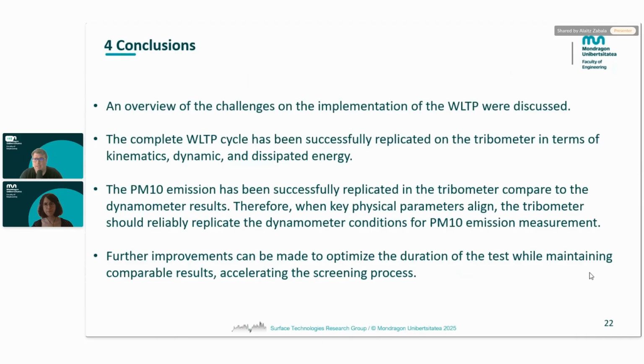We saw an overview of the challenges of the implementation of the WLTP standard. The dissipated energy that we introduce is quite important. So we developed the complete WLTP cycle in the tribometers in terms of the dynamic, kinematic, and dissipated energy, and we obtained really good results. We can say that the PM10 emission has been successfully replicated in the tribometer compared to the dynamometer results. Therefore, when key physical parameters align, the tribometer should reliably replicate the dynamometer conditions for PM10 emission, at least for the WLTP standard.